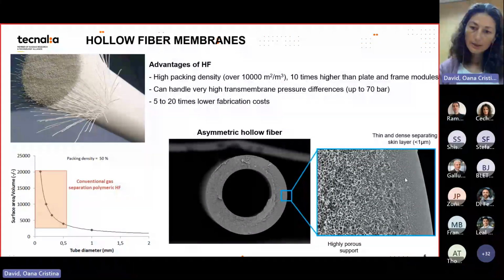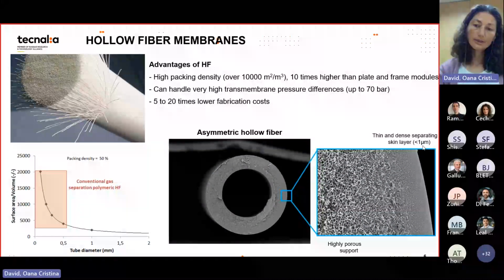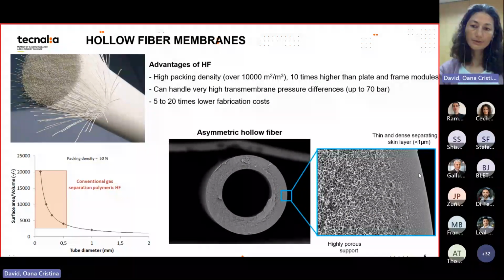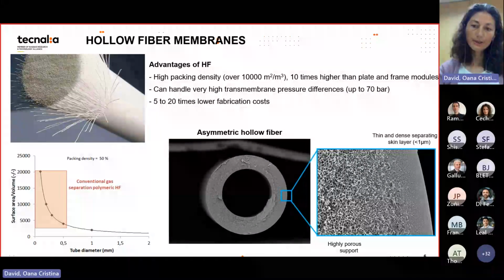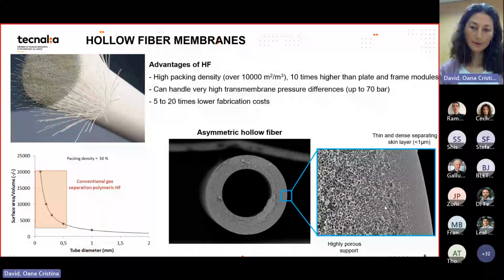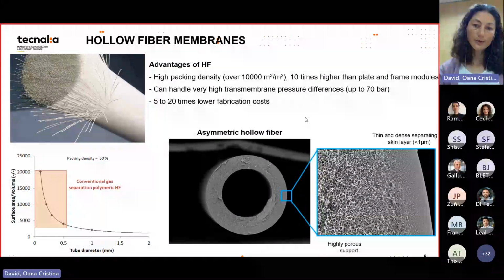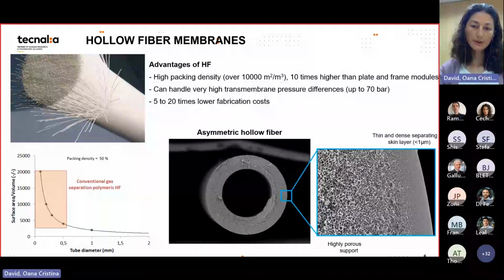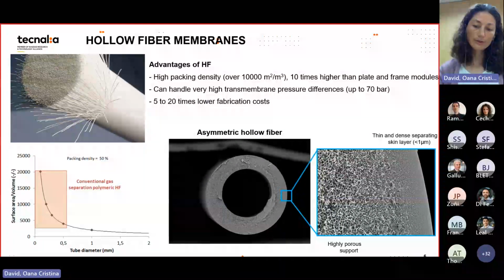And now going to the cross section, they are monolithic normally. We have a top layer, mostly on the outer skin, that is dense, and this layer ideally should be lower than 1 micrometer. Even 100 nanometer would be the limit, but it would be very nice to have that without defects. And then below that layer, we have a porous part. It's important to understand that both parts are made from the same material at the same time. So this is integrally skinned. And because of this process, in which the formation of these two parts occurs at the same time, normally the fabrication costs are much lower compared to composite membranes.